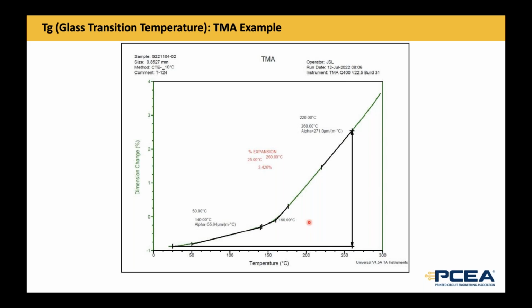It's often plotted over time as opposed to temperature, because the rate is set at a specific rate. Like in this case, it was 10 degrees C. You can see up at the top, it says CTE 10 degrees C. That's the IPC test method rate, and it's fairly accurate for most materials. But one of the problems that has been discovered is that this curve is not always such a hockey stick. Often it is a more smooth curve. So drawing the tangent lines and picking the tangent lines is very critical.